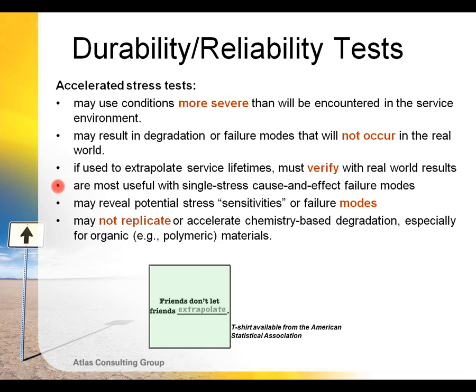Also, all of these tests, especially single stress tests, are primarily looking at single cause and effect failure mechanisms. In the real world, failure mechanisms are very often a series of combinations of multiple stresses or the same stress acting in different effects. For example, changes in temperature have a thermomechanical effect on a product exposed outdoors, but the changes in temperature also have an effect on moisture and can drive moisture in and out of a product as well. So when we start getting into multiple modes of failure or product change, you need to be careful how you interpret these results.